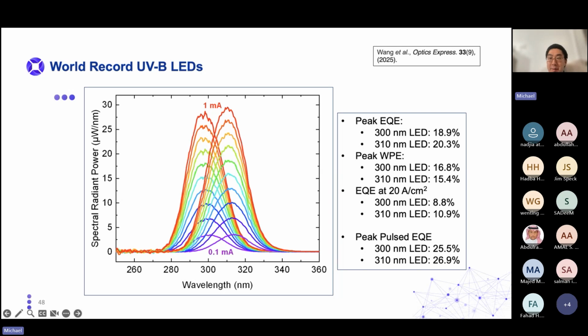The EQE at 20 amps per centimeter squared, which is a typical higher current density operation for LEDs in industry. So 300 nanometer LED is 8.8% EQE at 20 amps per centimeter squared, and 310 nanometer LED is 10.9% EQE at 20 amps per centimeter squared. So basically what is occurring is that our new material is operating at efficiency similar to the old published material, but at 20 amps per centimeter squared instead of 0.1 amps per centimeter squared.